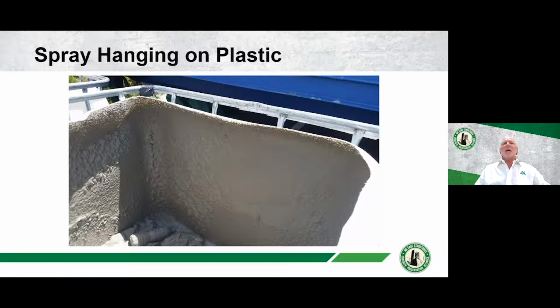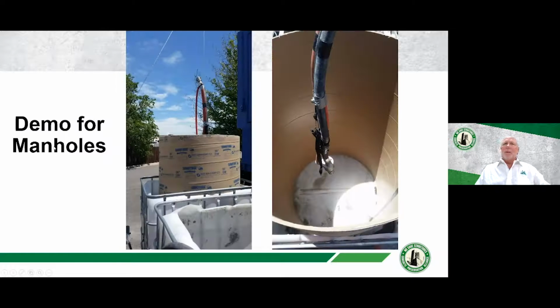You can see a little bit of sagging here. On here it was sprayed on somewhere in the neighborhood of a quarter to half an inch, but held up really, really well. Then the other part of the demonstration was being able to spray it in a vertical manner. This is a demonstration for manholes.